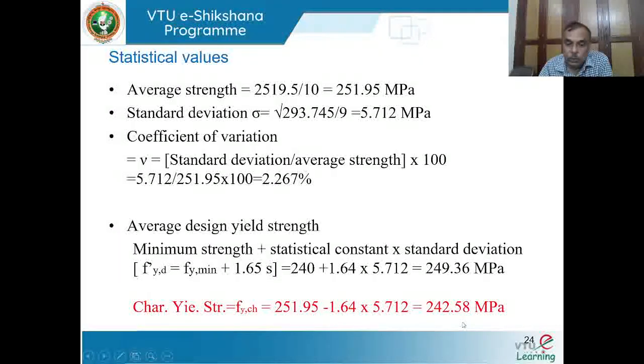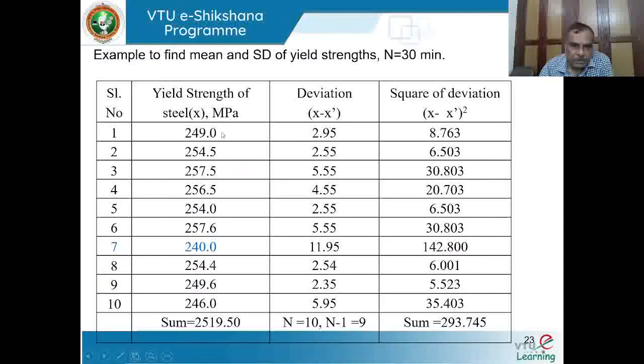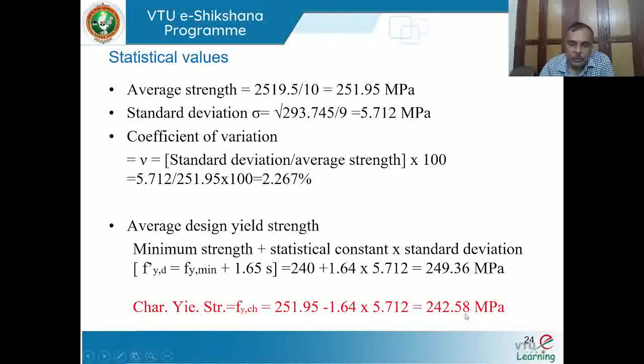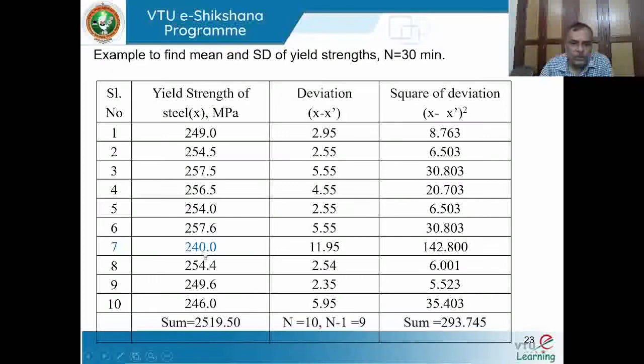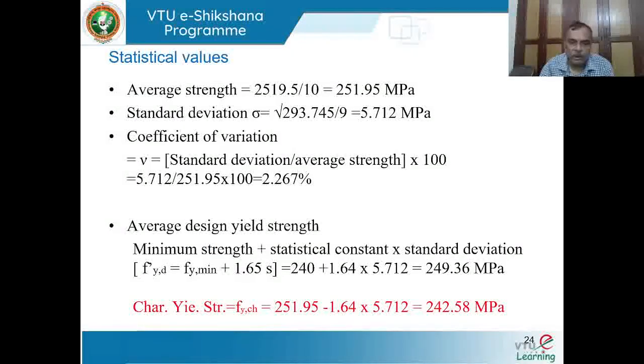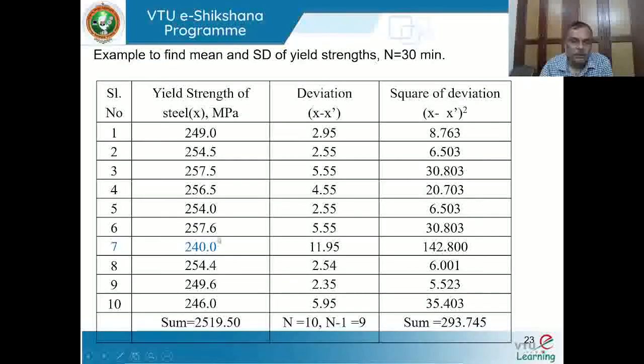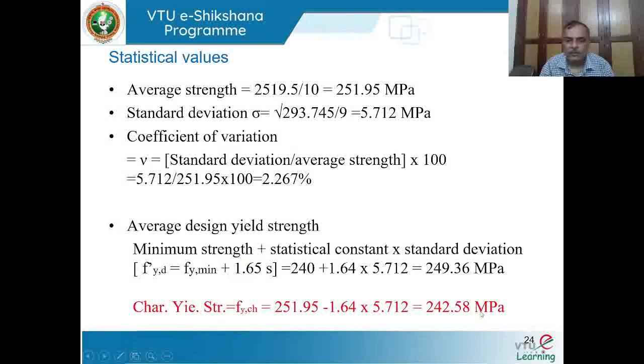At 242.58 and below that, you should not have more than 5% of the samples. Means if at all there is any value in the table, there should be only half a sample, means just one sample can have a strength which is less than 242, but otherwise all other strengths should be more than 242. So let us go back to the table. Kindly see that the values of the strength for all the samples are definitely more than 242, but there is only one sample whose strength is less than 242. So that is where the characteristic strength is the strength below which not more than 5%. Now here it is less than 5%. So there is only one sample which is less than this characteristic strength. So that is the implication of the meaning of characteristic strength of steel.